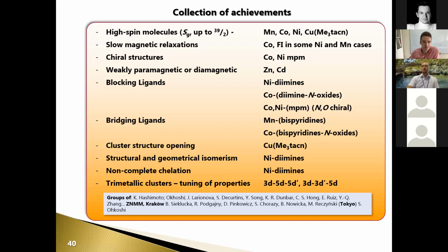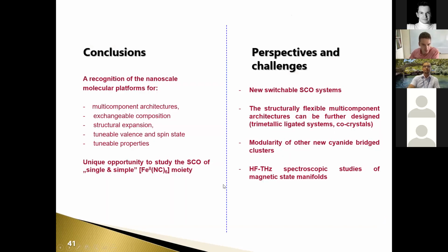So this is the score for the whole chemistry of this cluster. To finish, of course, high spin molecules, so magnetic relaxation, chiral class and structures, using blocking and bridging ligands with different composition, we could obtain also these characteristics. We observed cluster structure opening, structural and geometrical isomerism, non-complete chelation, and what is the most important, and this is the biggest success of these studies, the trimetallic clusters with the tuning of properties.